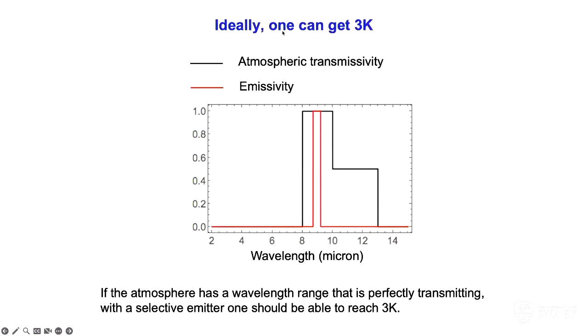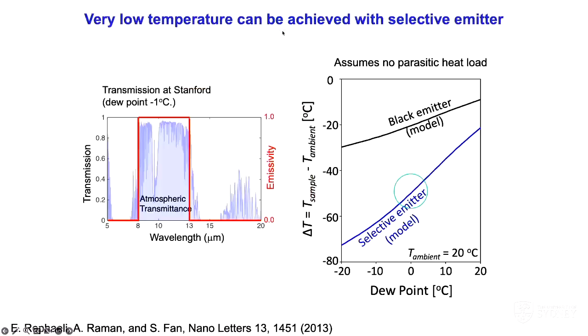So I've talked a little bit about the practical side of radiative cooling. It would be interesting to ask from a more fundamental side, how cold can you really go with this technology? This is a technology that's in essence trying to establish thermal equilibrium with outer space, and outer space is 3 Kelvin. So if the atmosphere has a wavelength range that's perfectly transmitting, 100% transmission, then you can build a selective thermal emitter with the emissivity that sits only in that perfect transmission window, and you should be able to get 3 Kelvin. In practice, no atmosphere is that good.